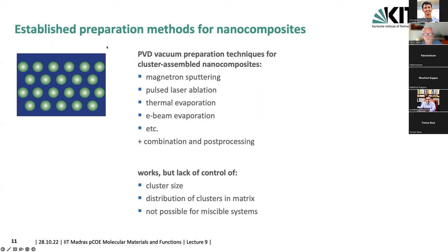What we do not have in such a technique is good control of the cluster size, and certainly of the distribution of the cluster size, because it's a nucleation and growth process, so we get a fairly wide size distribution. So if you're interested in very small embedded clusters with a narrow size distribution, that typically cannot be achieved by such a simple process as shown here.